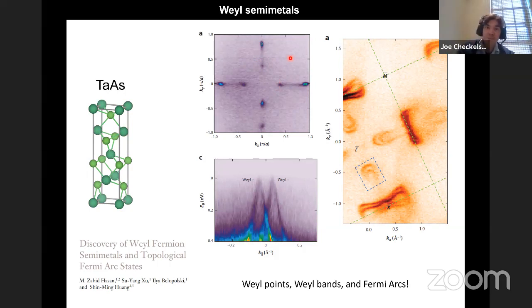And there are these points in momentum space. There are actually many points, because one way of thinking about it is that for almost every symmetry you have in a crystal, you end up doubling the number of these Weyl points. But then, for example, what you can look at is the dispersion. If you look at the energy dependence around these points, you can indeed see they have these linear type crossings.